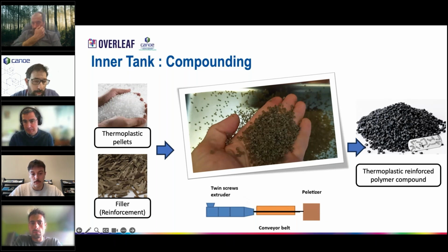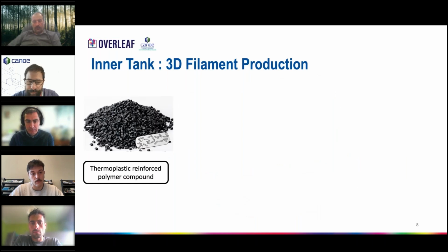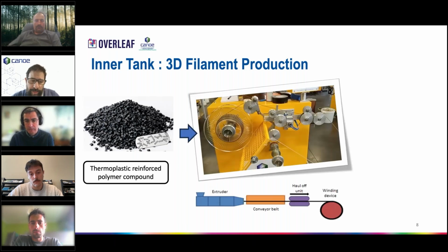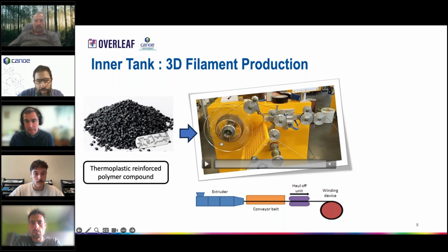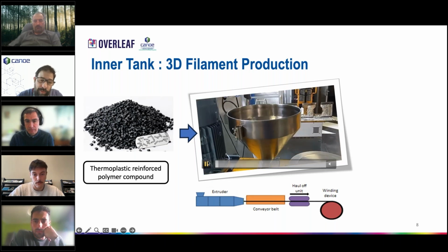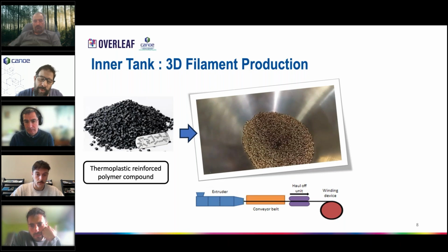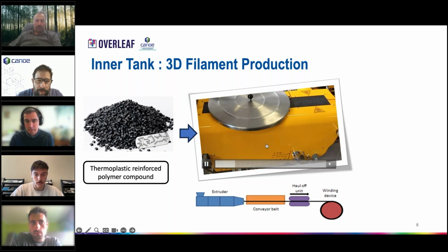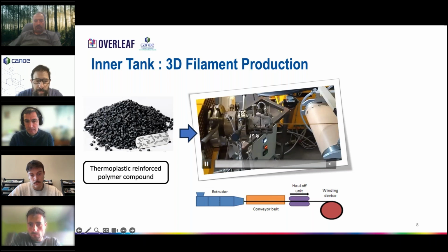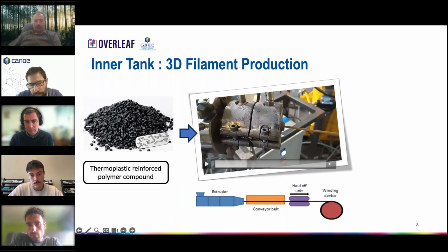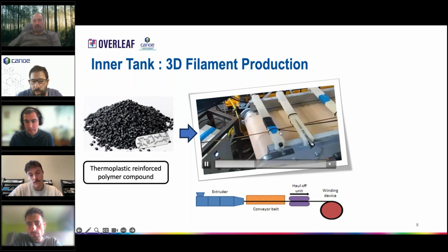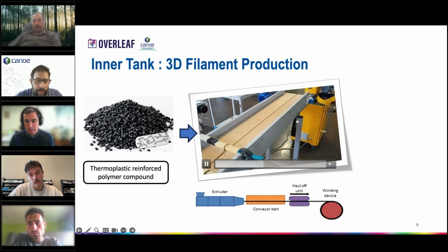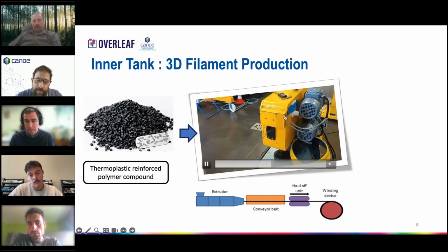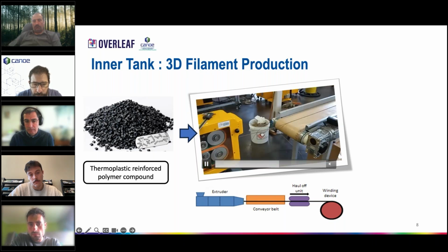Then this compound was used in another tool in order to manufacture the 3D filaments. The 3D filament is made with a more or less similar process, but this time it is not a twin screw extruder, it's a single screw extruder, where the material is fed directly into the main hopper and then melted, through a specific die of 2.8 millimeters in diameter. We make the filament, and then we need to control the cooling at a very accurate temperature in order to get a very circular and continuous filament.